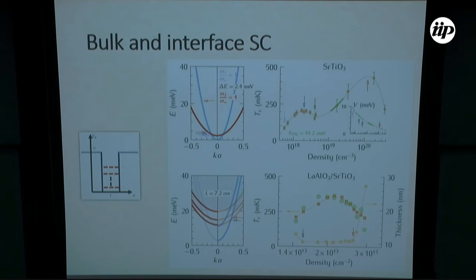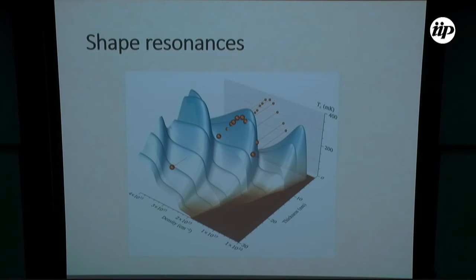And another point: now if we look at this diagram in full, this is what we observe. This is all the calculation they did as a function of thickness and as a function of two-dimensional carrier density, where you see the shape resonance, and you see the doping effect that are strongly correlated. And as we move with the field effect, we move along a line along this complex surface. And so that's the reason why we probably observe this shape, with a decrease of TC in the overdoped regime, even if we are far from the decrease of TC in the three-dimensional compound.